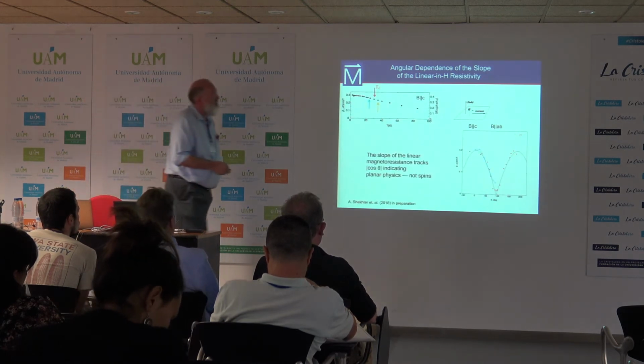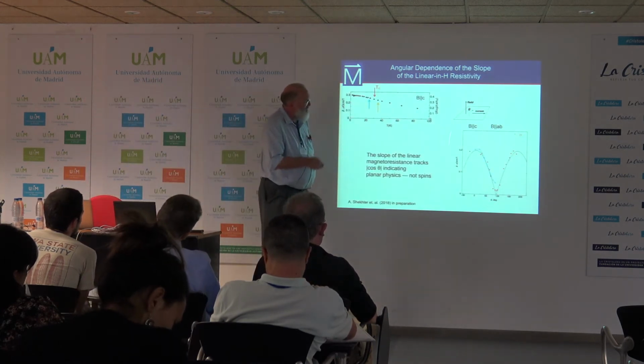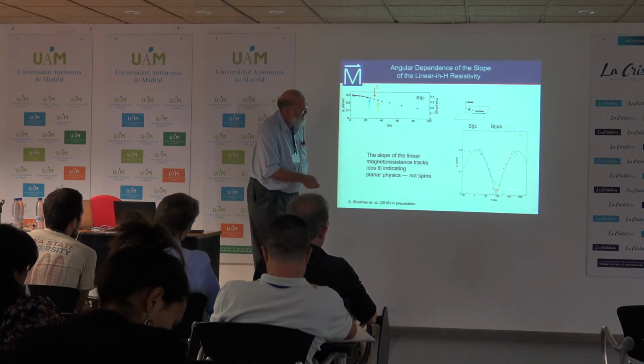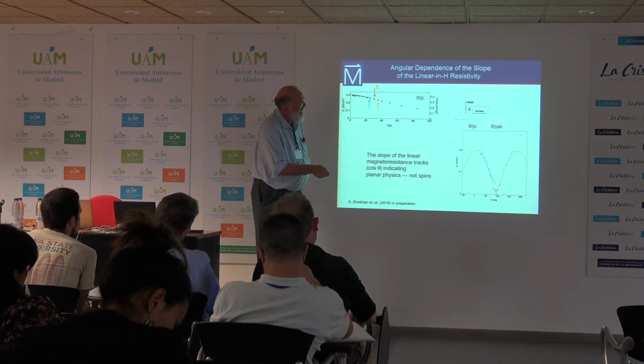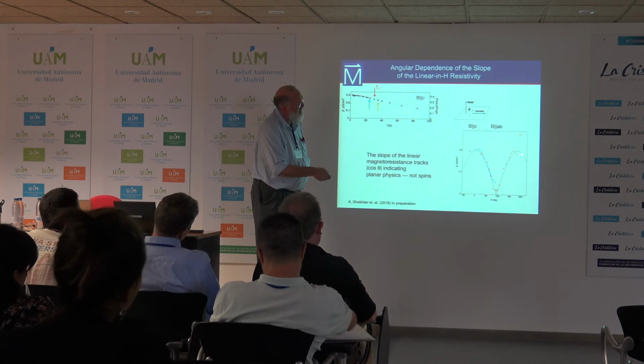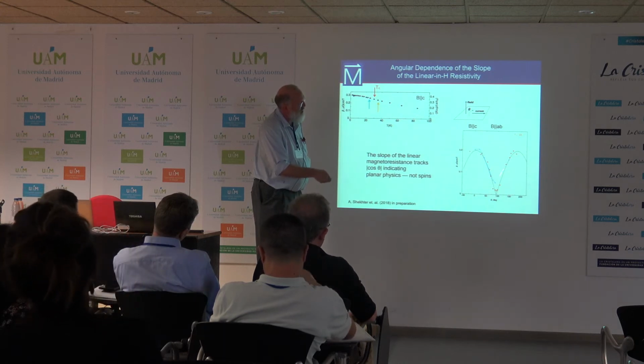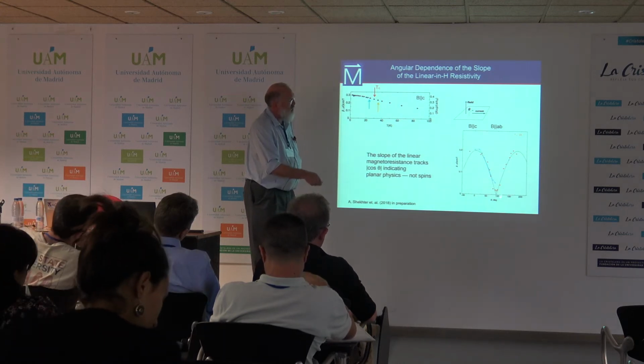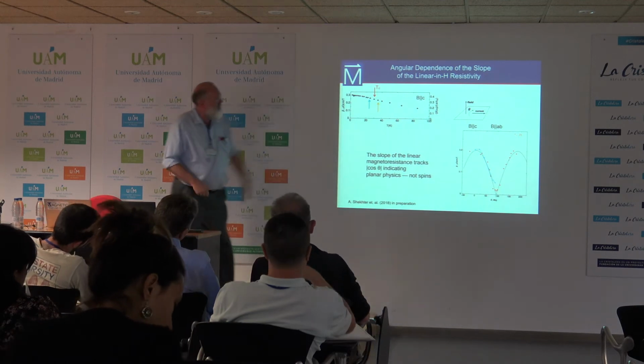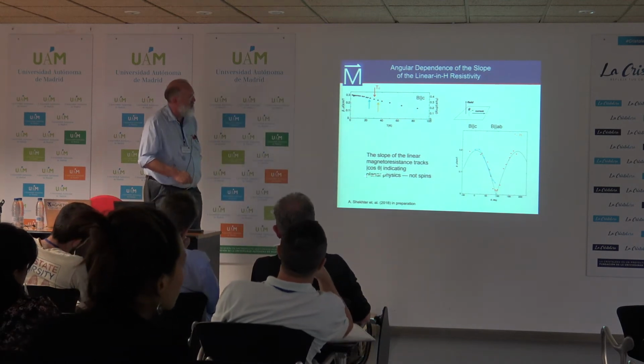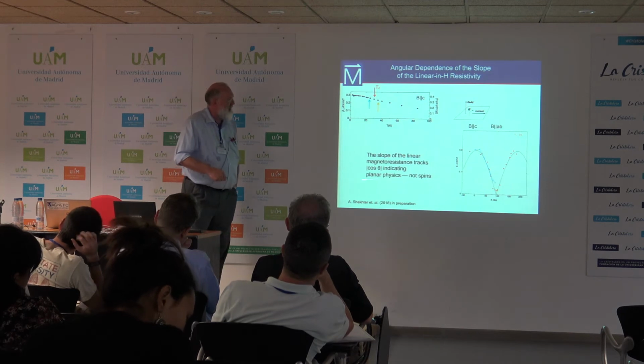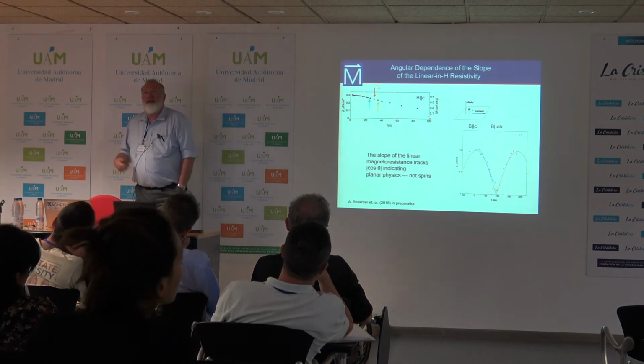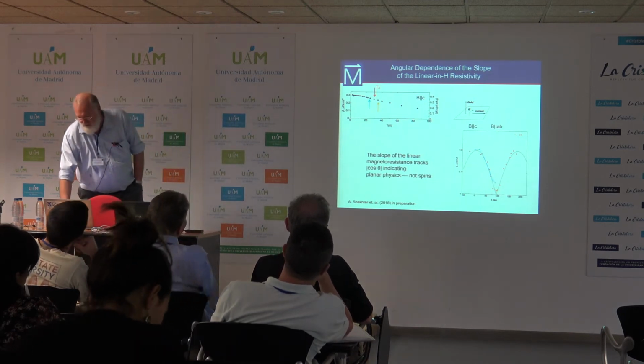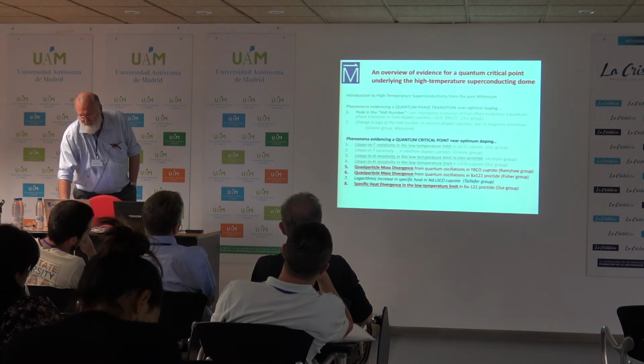And what he finds in this plot of the slope beta versus theta, the degree, here when you're perpendicular to the planes, you've got a maximum value for the linear in H coefficient, and then that value of that coefficient follows a magnitude of cosine theta over quite a range of theta. So the slope of the linear magnetoresistance tracks cosine theta, absolute value, indicating there's some sort of planar physics. It's not arising from spin interactions with the magnetic field.